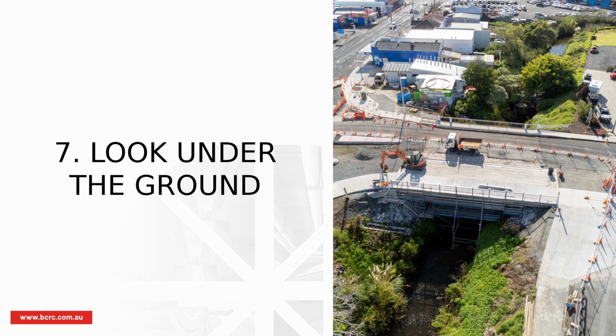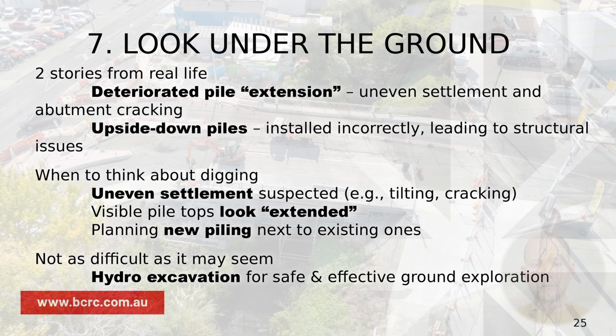Lesson 7. I'll tell you two stories here. One about deteriorated pile extension. Once we were building a new bridge next to the existing structure. At the time of the piling, the contractor reported a significant crack in the older abutment of the existing structure. What happened is one third of the abutment, as soon as the piling commenced, cracked and started tilting a bit.